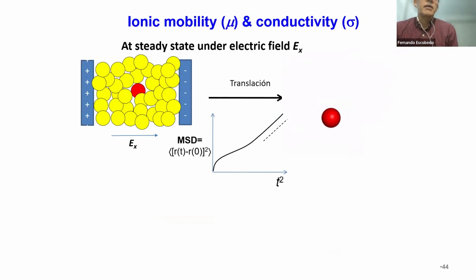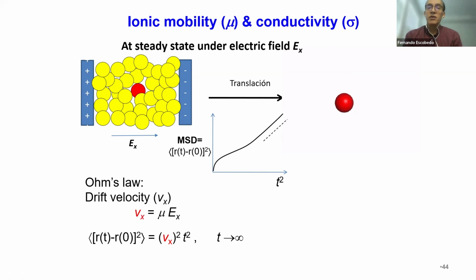Now, as far as the methods, if you want to probe ionic mobility and conductivity, typically we will have to use an electric field, so we apply an electric field to be able to see the motion of these ions in some reasonable time, and then you will track the motion of the ions through the system, through this polymer. And you can characterize that mobility by using the mean square displacement, this MSD, as a function of time, or here as a function of time squared. So the more it moves, of course, the larger these changes will be, and also that may be reflected in the slope. You can apply Ohm's law that basically relates the drift velocity Vx with the applied electric field to be able to extract what this drift velocity is. And then that can be extracted from these plots of the mean square displacements. So in the simulation, you can extract this drift velocity that way.